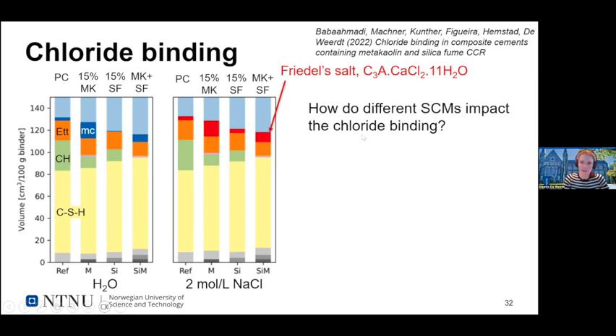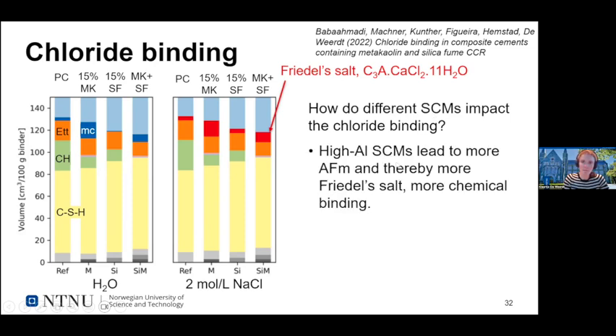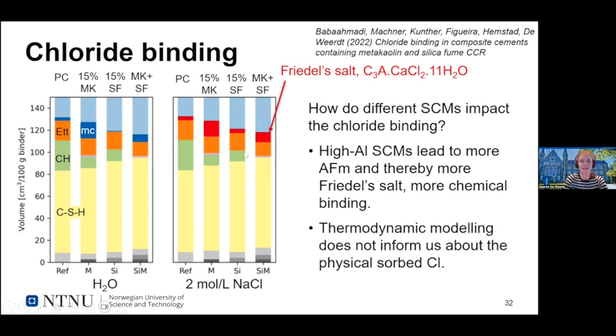So how do then these SCMs affect the chloride binding? When we have aluminate-rich SCMs, such as metakaolin, we'll form more of this AFM, and more of this AFM results in more Friedel salt and thereby more chemical binding. But the problem is GEMS doesn't tell us anything about the physically adsorbed chlorides because that's not included in the current CSH model. So we can't say how these changes in the CSH affect the physically sorbed chloride.